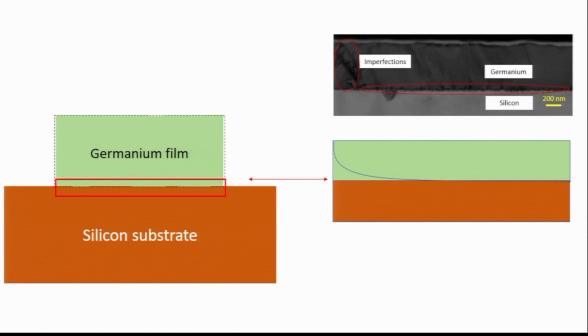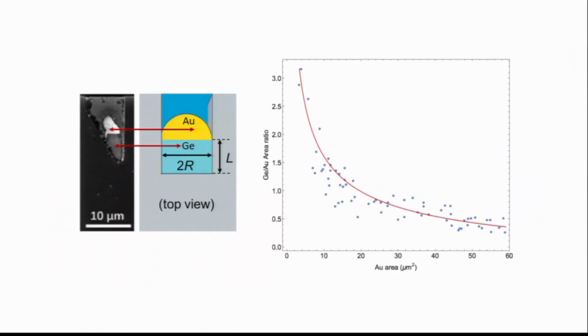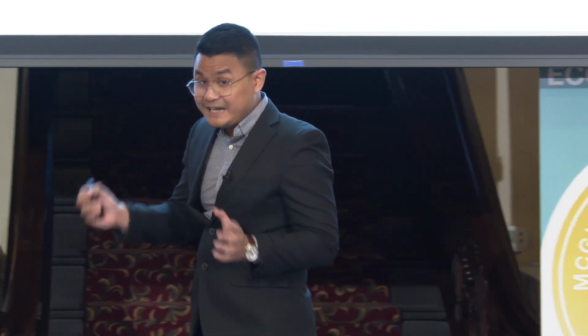You see, as we grow from left to right, our imperfection stays at the bottom, at the interface of germanium and silicon. So this is a really interesting result we got. And furthermore, we're also able to control the size of the germanium film by controlling the size of the gold catalyst. And if you have friends who are chip designers, this is really big news, because in reality, in the chip design of optical circuits, we need those optical sensors and lasers to have precise dimensions. And we can control the size by controlling the gold catalyst size.